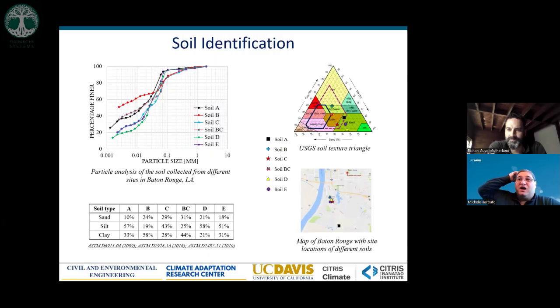We started by investigating and characterizing the soil around the river. We found that as long as you move at least a couple of miles away from the river, you never are in the optimal region where you can just use the material and make a block, but with some additional chemical stabilizers, some amount of cement, we are in that suboptimal region that can still be used.